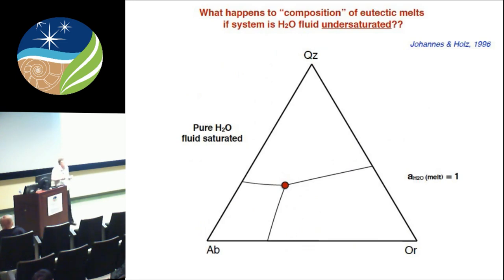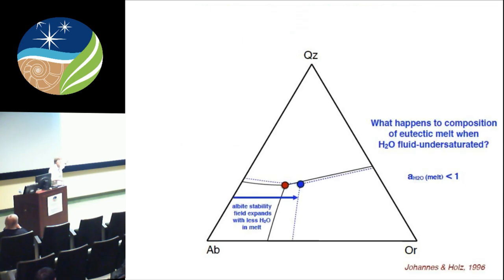We can prove this, we think, looking at the geochemistry and the mineralogy. So this is the location of the eutectic at 4 kilobars, say, and this is pure water saturated. When the activity of water is 1, that's where it's located. Johannes and Holtz have done experiments at the same pressure, and they looked at mixed CO2-water, so undersaturated with water. What happens is that the albite stability field grows at the expense of the orthoclase. This is another proof that if you increase dissolved water, you shrink albite, and orthoclase doesn't care, or sanidine. But if you lose water, albite grows at the expense. So this lends support to the concept of sanidine hygrometry. Anyway, the albite field expands.